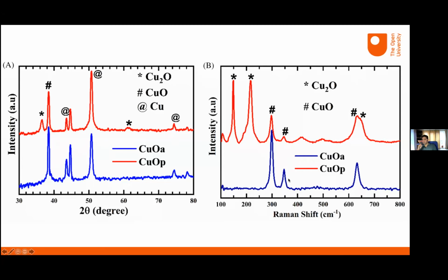And this is an important result, because what we were thinking is that as time goes, these copper oxide radicals interact and nucleate along the nanowire, forming a shell of Cu2O on top of the nanowires, with CuO inside.